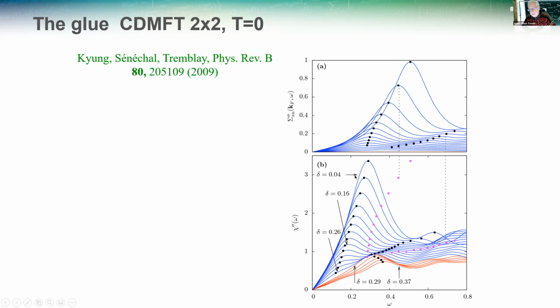Actually, I think Christian was the first to see these two peaks. And you see that if I shift by the gap here, these peaks follow each other. So you can conclude from this that what's imprinted in the pair wave function are these spin fluctuations.